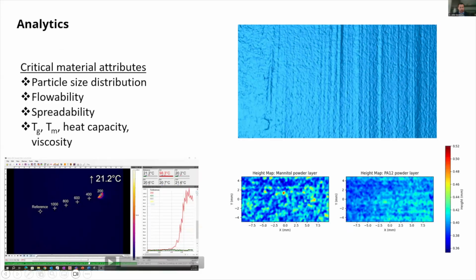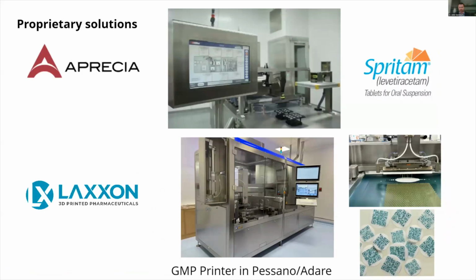And when we use thermal imaging, you see the influence of the material temperature based on the scan speed of the powder. So you have increasing scan speed of the laser. You see that the temperature is clearly changing depending on the energy input. And we're learning that the heat capacity of the polymer has a very high influence on the process, so does the viscosity. None of this is surprising. All of this is well known. None of this is known in the pharmaceutical field, so we have to build up a lot of knowledge from scratch by learning from people that have done it before. But this has to be established to really demonstrate that the technology is a feasible one for pharmaceutical manufacturing.